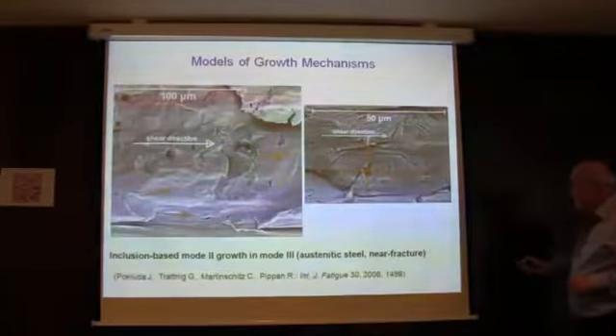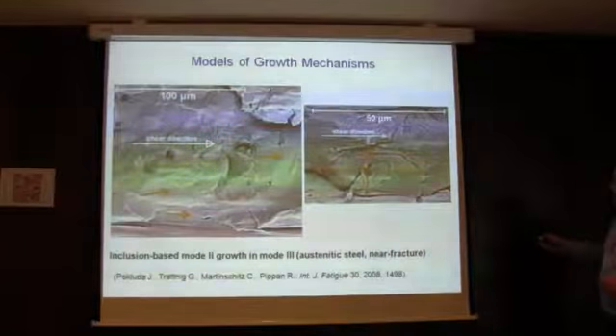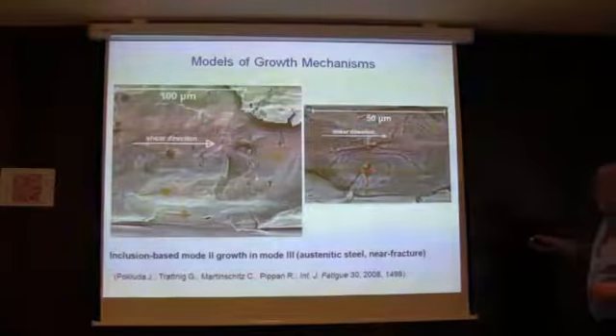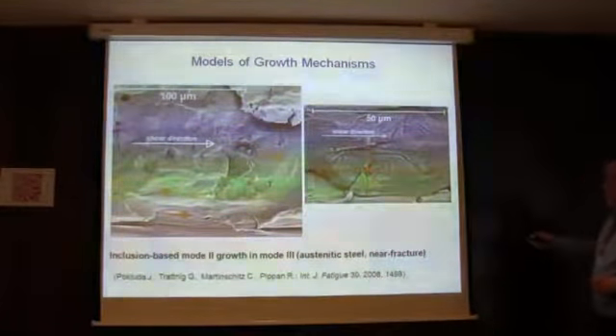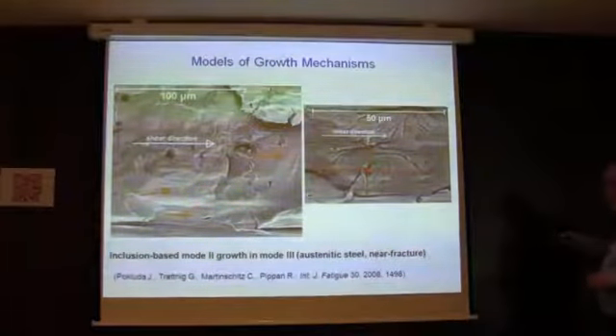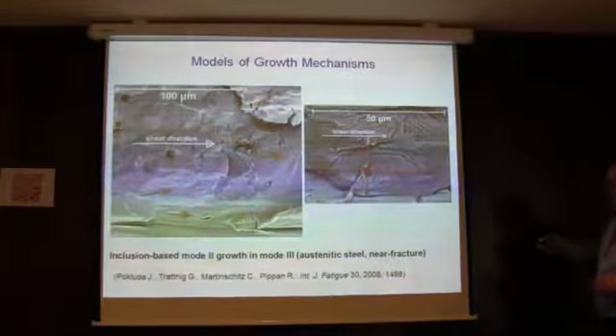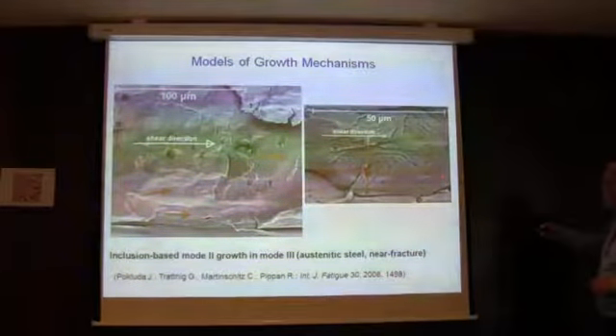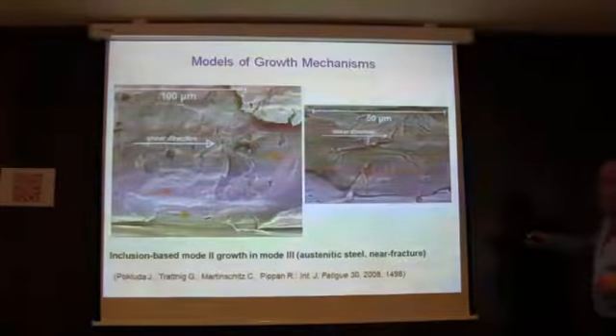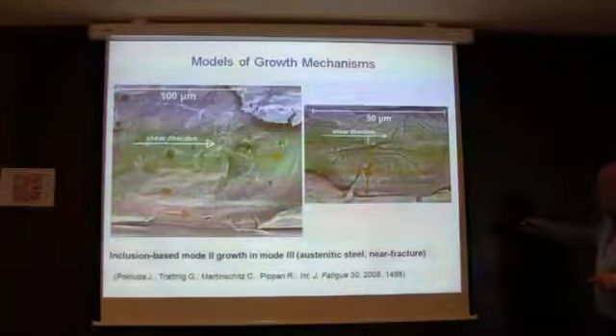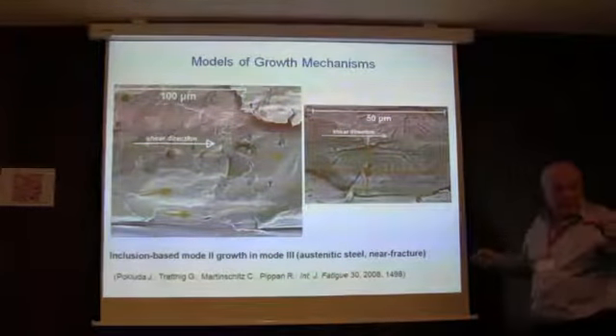And this is also interesting because you have an inclusion here, and you can see the propagation in mode 2 this way, and mode 3 this way. And you can see that the mode 2 propagation is faster than mode 3, even if in this case the K2 factor was a little bit less than the K3.